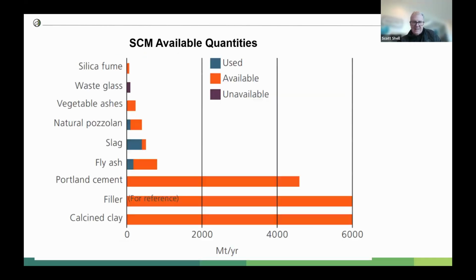There's another challenge with these SCMs, that they're just not available in large enough quantities. You can see here the Portland cement, we make over 4 billion tons of Portland cement globally every year. And there's only about 8% or 10% or so as much fly ash or slag as there is cement. So it can never replace at a high level on a global basis the Portland cement or clinker in those blended cements.